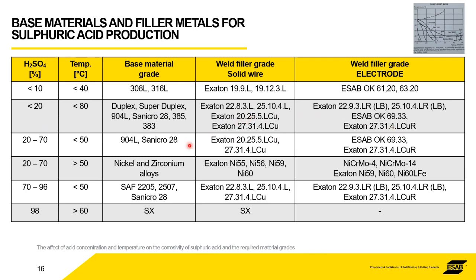So we're still using stainless steels at these kinds of levels, and it's only when you get above 50 degrees, so you're getting over 20% strength and over 50 degrees, that we need to start using the nickel grades. So again, the nickel grades and zirconium, of course, but nickel grades of base metals. There's a large range of nickel-based solid wires to match the accompanying base metal. And again, there are also electrodes as well. So these are very highly alloyed with nickel, but they're available in covered electrodes.